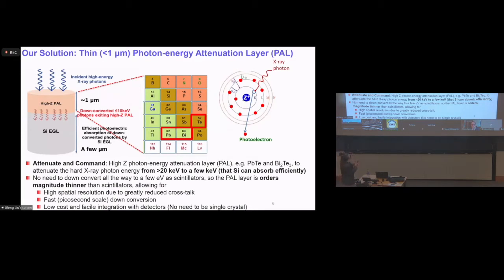In this case, you're looking down the periodic table, looking at those big atoms. Big atoms are important here, not because they're heavy, but because they have a lot of positive charge on the nucleus. So the innermost shell, the K shell, has a very strong attraction with this, and essentially the binding energy is large, and then you get a high frequency resonance, so it can interact strongly with the hard X-ray at greater than 20 kilo electron volt energy. So essentially, our candidates include, of course, lead, but lead is not so healthy, you know. So eventually, when we do the experiment, we use a compound called bismuth telluride, which is much safer to use.